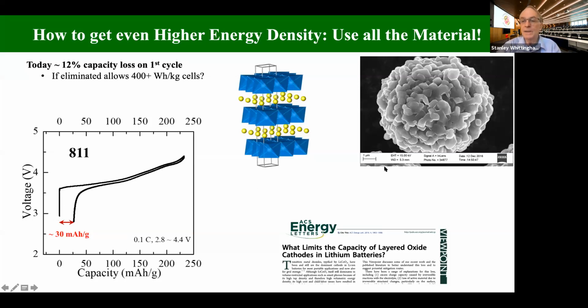And I should point out all the commercial materials today use what we call meatballs. So these are 100 to 200 nanometer primary particles joined together to form these from about 10 to 20 micron secondary particles. And in a commercial battery, it'll have this size particle plus some smaller ones so they pack even more efficiently. So we wanted to know what caused this and how could we solve it.